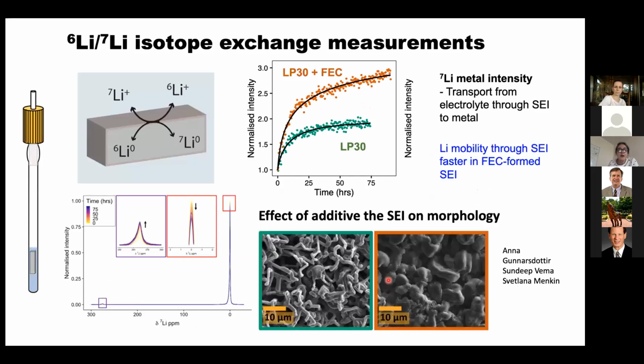And this is an example where we're trying to understand how this works by looking at the normal electrolyte, and this is the additive fluoroethylene carbonate. And you can see that if you add different additives, you get very different morphologies of dendrites. So this is the standard electrolyte, and this is the FEC additive. And the reason that this grows in more nodules and less dendritic structures has got to do with the rate of the lithium transport through this SEI, this passivating layer.